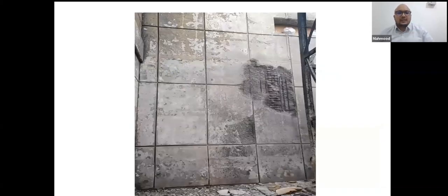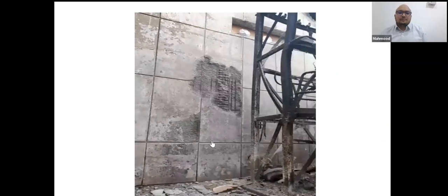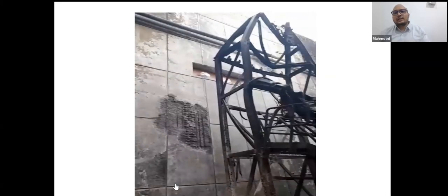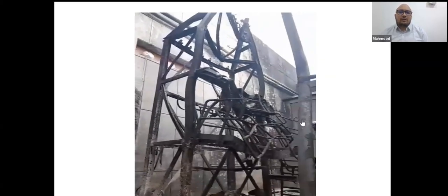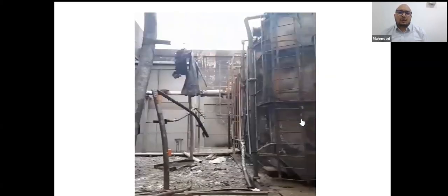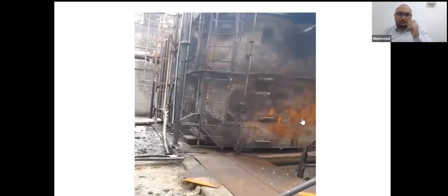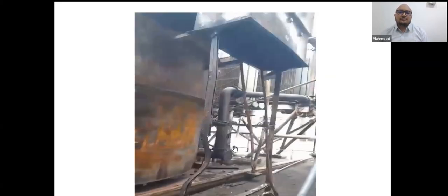This is a fire damaged area. Even for the fire damaged area, they will chip out all the damaged concrete and follow the same technique: epoxy bonding agent plus the same polymer modified shrinkage compensated repair mortars.